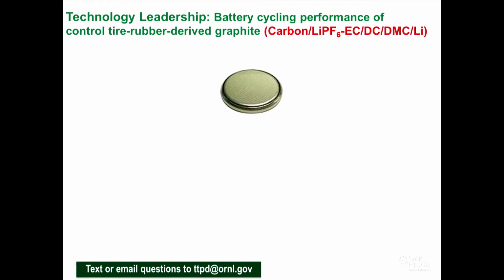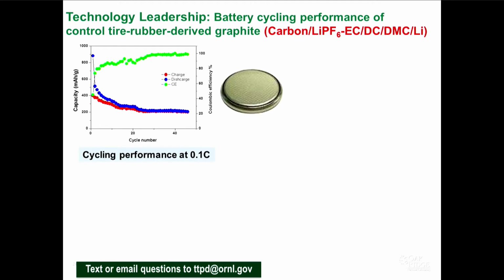So what I'm talking about right now is the one I talked about. You take the powders, you just go through the pyrolysis and make the graphite, and that's what you have. So you can look at the cycling performance at 0.1C. The capacity after few cycles goes down. It saturates, you can see the red and blue, both charge discharge curves, and it's plateau, but you have only 200 milliamp hour per gram.